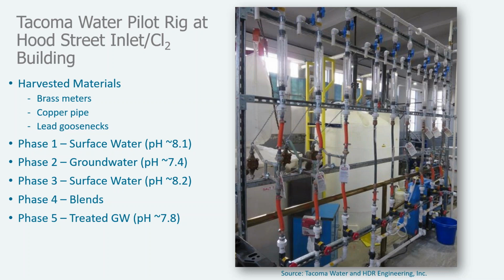And so, of course, these were an area of focus of the study to see how the lead was behaving in the switching of the water chemistries. So at Hood Street, the way the test was set up was phase 1, the entire test rig was equilibrated to the surface water, which had about a pH of 8.1. And after phase 1, 1 brass meter, 1 copper pipe, and 1 lead service line would be harvested and then sent to University of Washington for scale analysis.